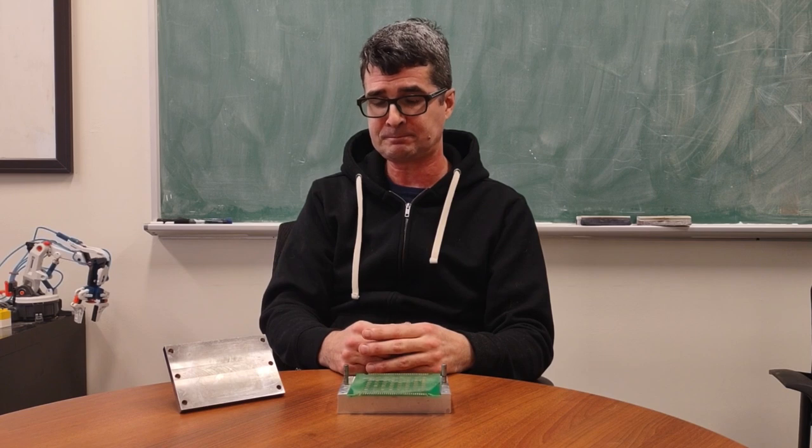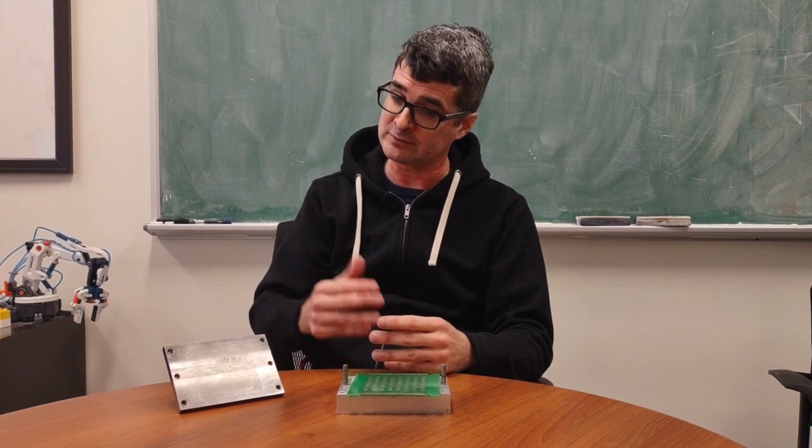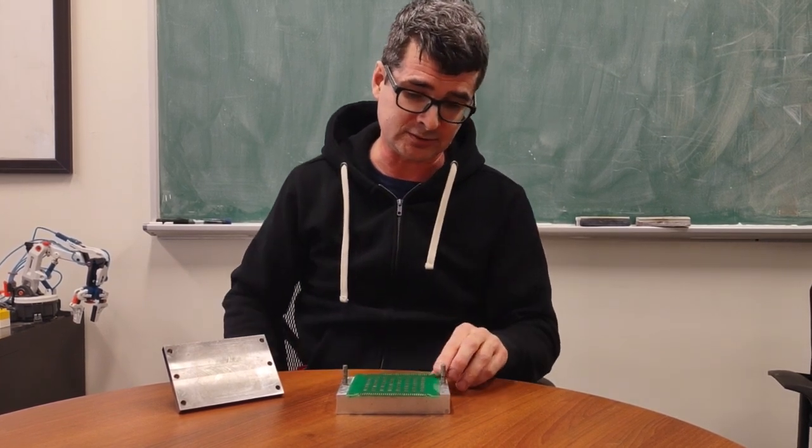And then we retrieved all of that lithium, those 64 different lithiums, dissolved them so that we could do elemental analysis. So we did ICP and determined that some dopants and some synthesis temperatures led to greatly reduced transition metal dissolution. And some of those materials also showed higher capacities than the undoped. So we were able to make better materials, and we could do it in a very accelerated manner.